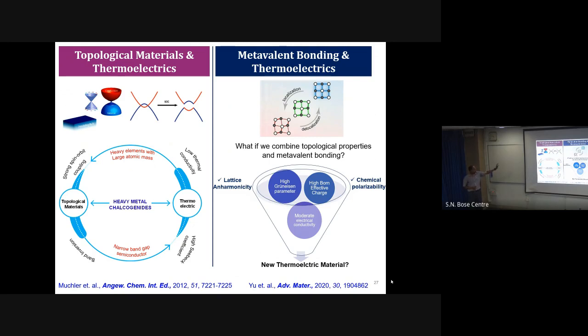So, let's see the lone pair effect in this material. In topological materials and thermoelectrics, as I told you, both have heavy metal chalcogenides, connected by low thermal conductivity and high Seebeck value. Topological materials have band inversion and strong spin-orbit coupling, and metavalent bonding in thermoelectrics has a high Grüneisen parameter, lattice anharmonicity, and high Born effective charge. It has high chemical polarization, so they have low thermal conductivity and moderate electrical conductivity, giving rise to a new thermoelectric regime. So now, what if we combine topological property with metavalent bonding?